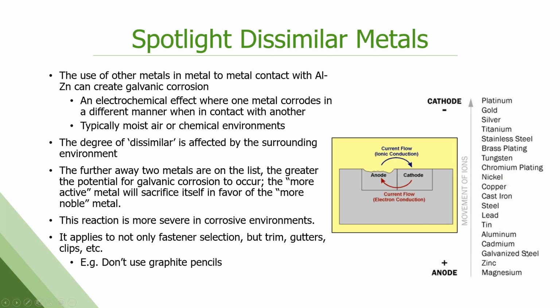You can see that galvanized steel and then aluminum zinc would fall right down in here. It's quite a ways from copper, quite a ways from stainless, quite a ways from titanium. So in a corrosive environment, that distance becomes problematic. The items at the bottom here will sacrifice themselves to protect items at the top of this list. So we want to avoid that, and it does happen in corrosive environments. Only in a benign environment do you really not have anything to worry about.